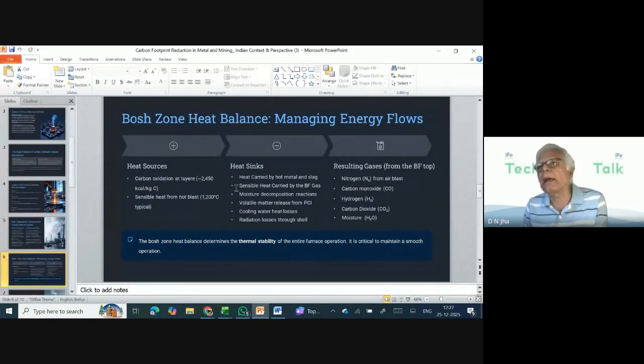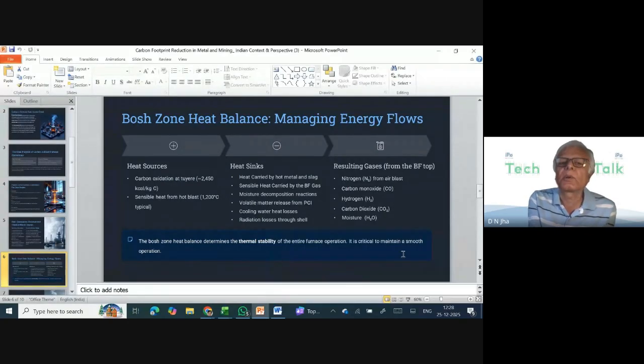And if we look at the amount of heat that is required for melting the hot metal and slag, that is roughly 40% of the entire heat that we are talking about. So the melting heat, the sensible heat that is taken by the hot metal and slag, constitutes at least 40% of the heat requirement. And 40% is not a small energy that we are talking about. So it's a very important aspect to consider.